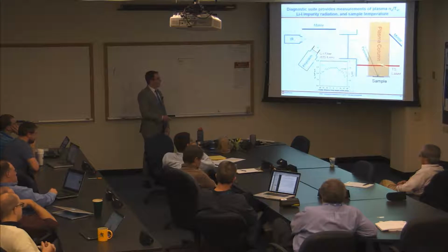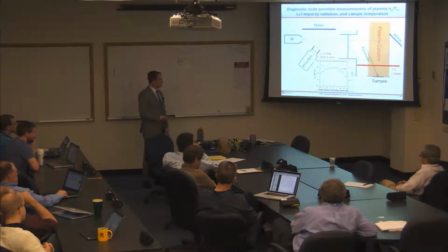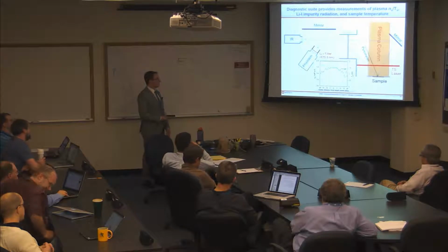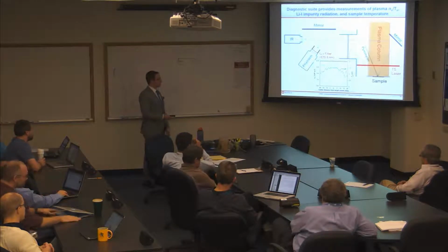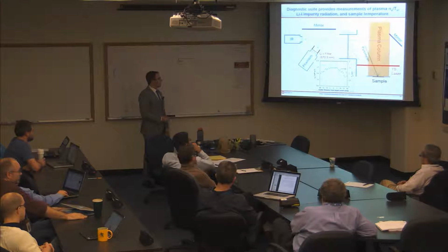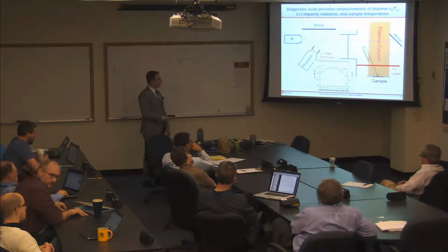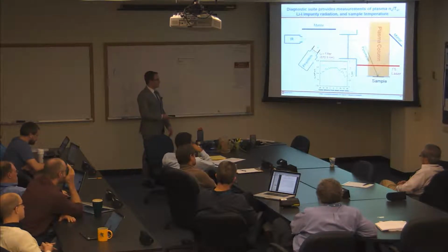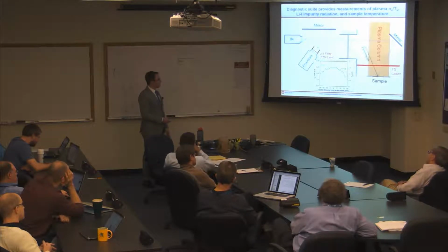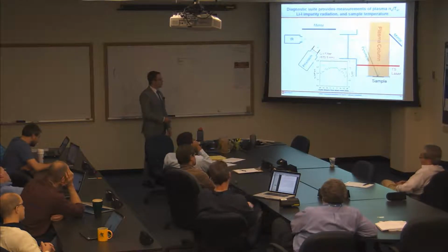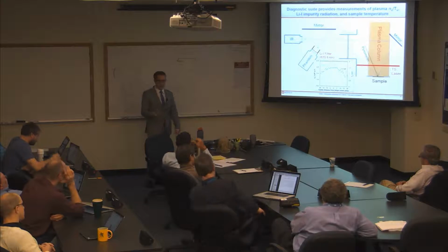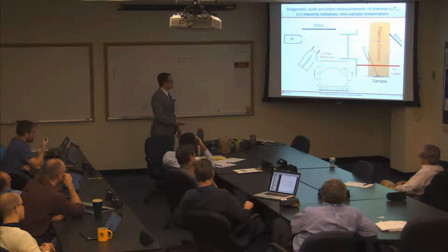We also had a Thomson scattering laser to get very high resolution density and temperature measurements very close to the surface. So this was typically about 10 millimeters away from the surface. And an example radial profile of the temperature and density is shown here. So as you can see, it's pretty Gaussian with resolution of about 2 millimeters, maybe less than 2 millimeters. And so you can use these densities and temperatures to actually determine what your plasma flux is, which is nice.